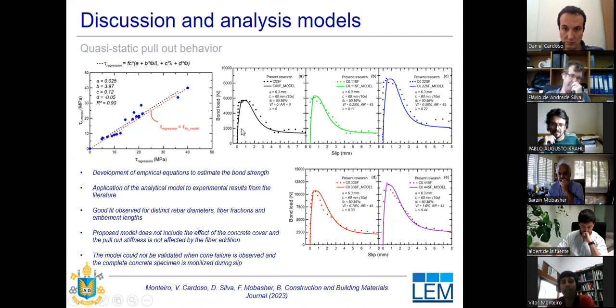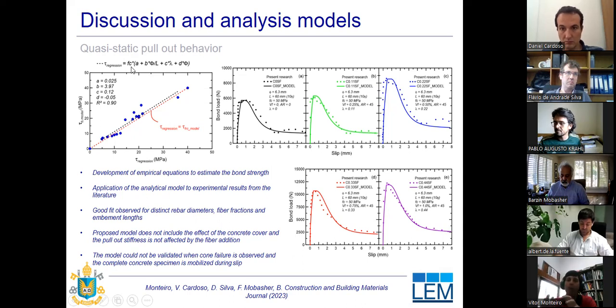The analytical model was applied to the literature results. Distinct parameters were changed, like the rebar diameter, the fiber fraction, the bonded length of the rebar, and the compressive stress. So changing those parameters, we applied the analytical model and it presented a very good fit for those four major parameters in our model.